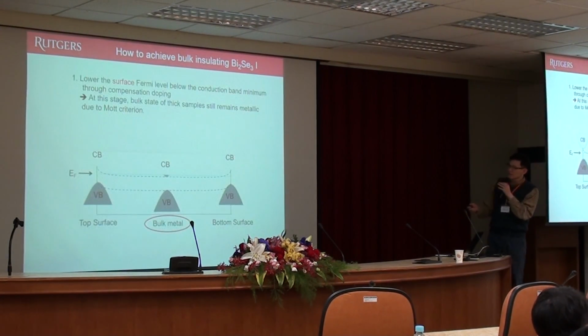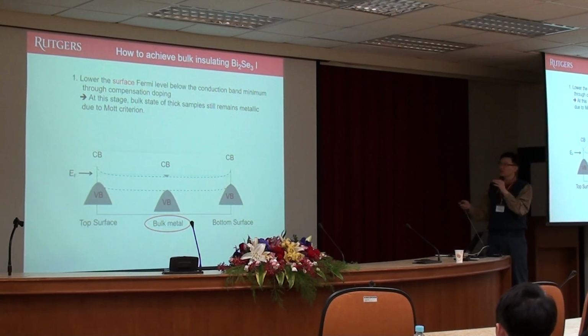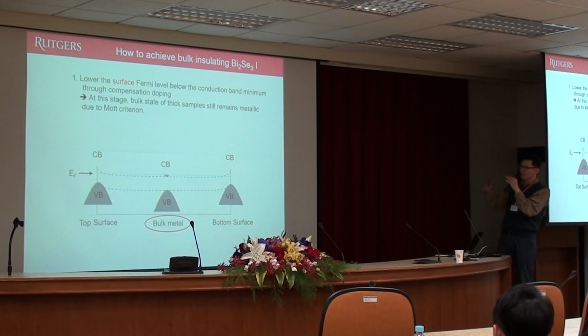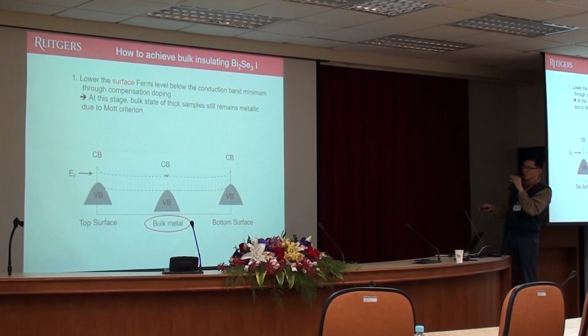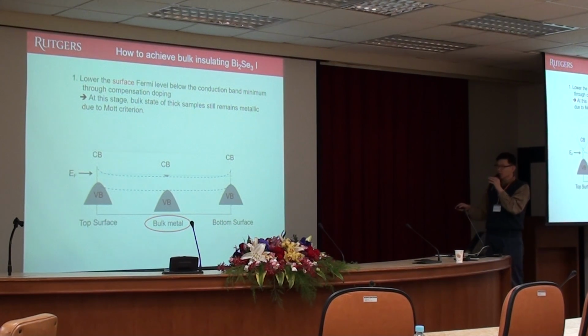Maybe, but there always is hope. It turns out that there's maybe, probably not the only way, but one way is using thin film. By making films thin, it turns out that you can really overcome this problem. The way it works is, let's say somehow you manage to make the surface could be on